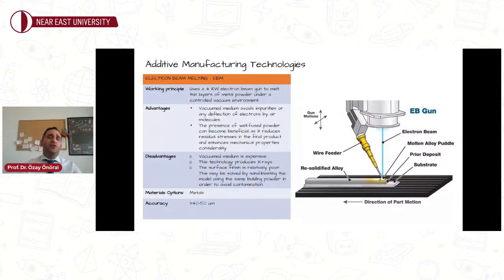Another fabrication way I'm going to talk about now is electron beam melting. Typically, selective laser sintering, selective laser melting, and electron beam melting are quite similar to each other. But in this device, we are not using a laser. In this technology, the electron beam gun is located at the top of the vacuum chamber, and the operation starts with sending an electron beam from the filament. A series of coils is used to control and scan the bundles, and by accelerating the electrons between the anode and cathode ends, the energy required for the melting of the powders is produced. Using an electron beam instead of a laser is the main difference between electron beam melting and the selective laser technologies.